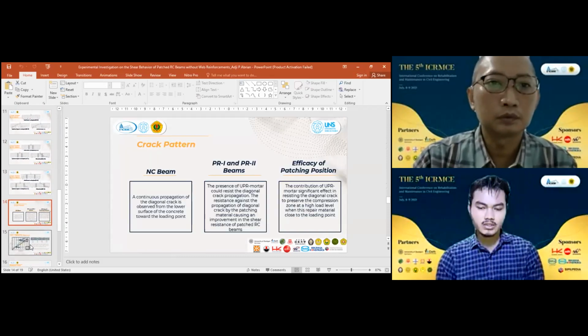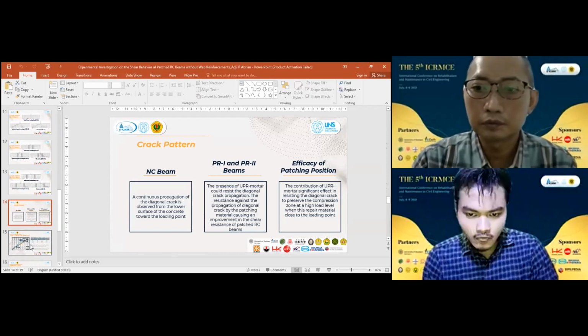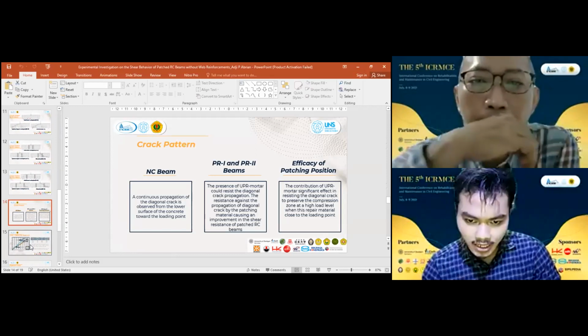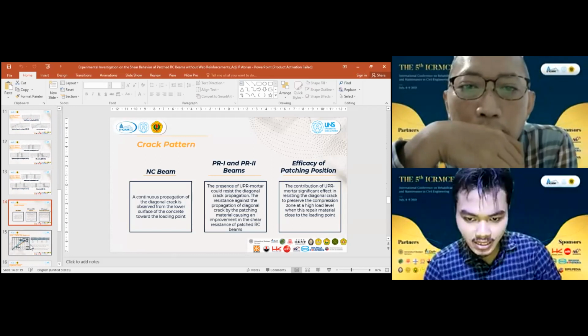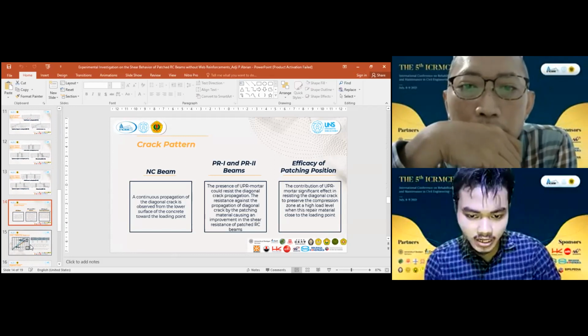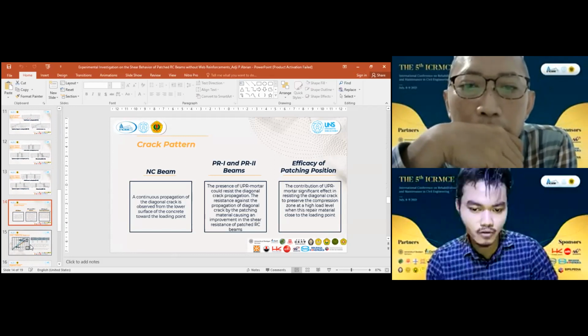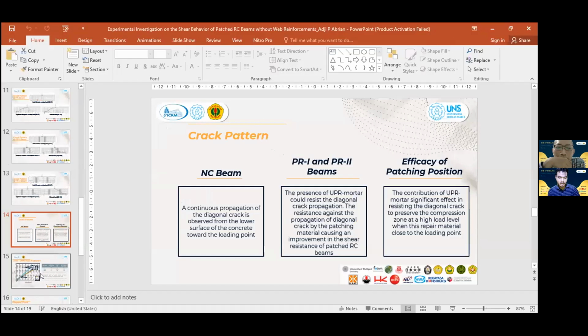Yes, it is the basis of UPR mortar that resists the diagonal crack propagation. The resistance against the propagation of the diagonal crack by patching material causes an improvement in the shear resistance of patched RC beams. And then the efficacy of patching position: the contribution of UPR mortar has a significant effect in resisting the diagonal cracks to preserve the compression zone at a high load level when this repair material is close to the loading point.